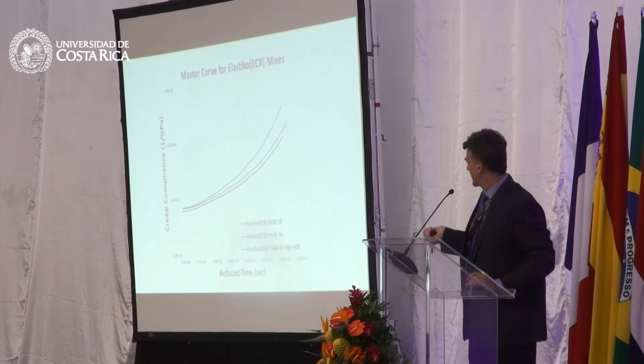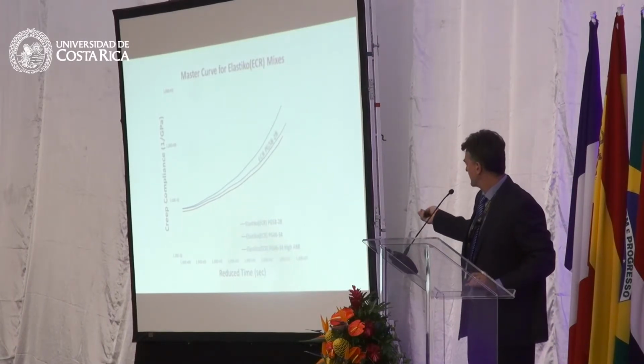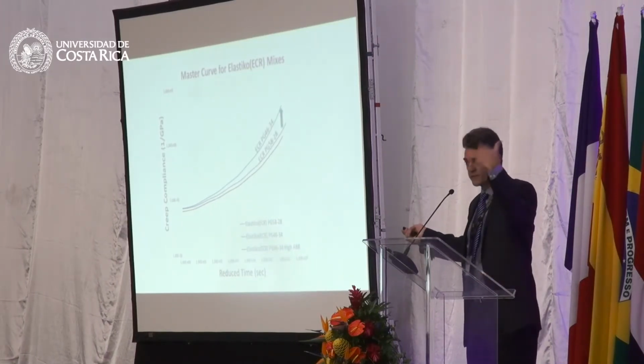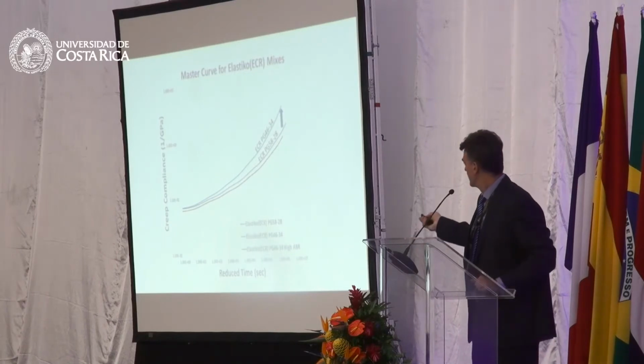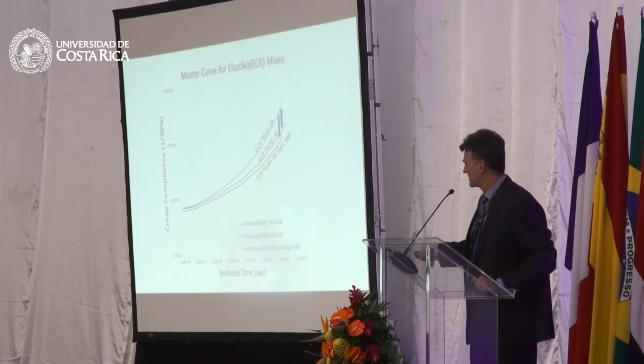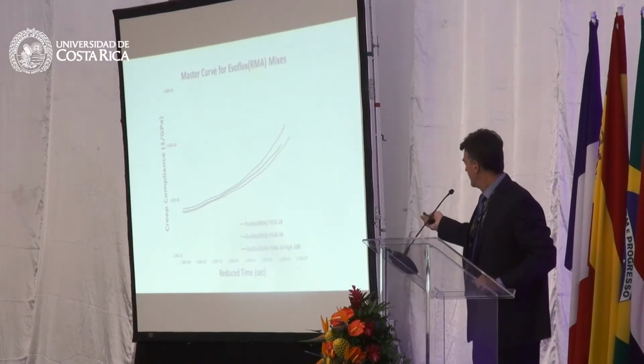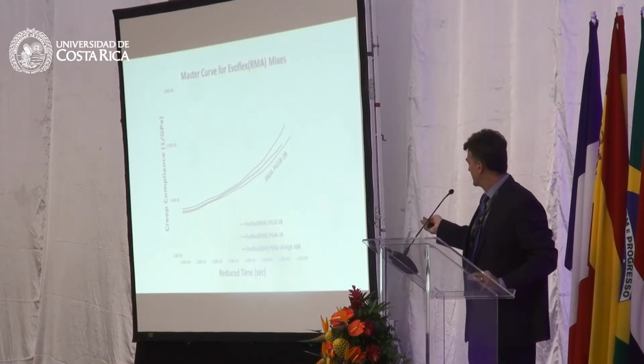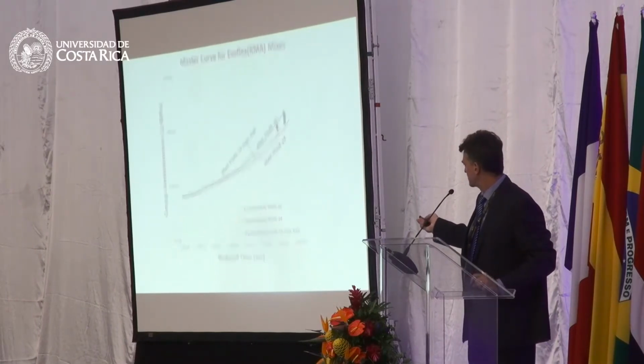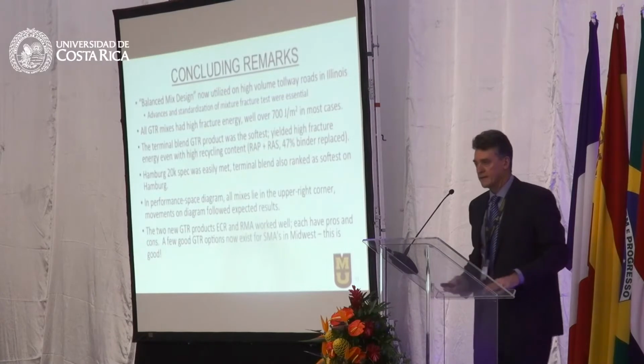Same thing for the Elastico mix. We saw the same trend of softer, more compliant mix with the -34 binder and back towards the control. The stiffest mix was the EvoFlex, and it showed less spread but a similar trend.